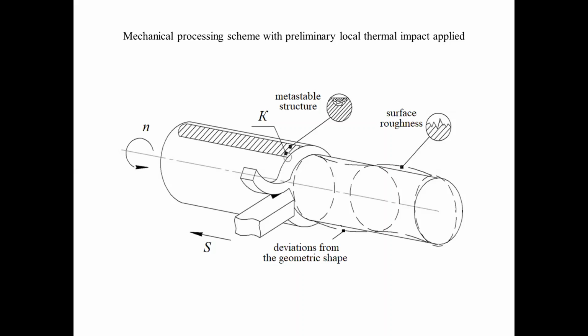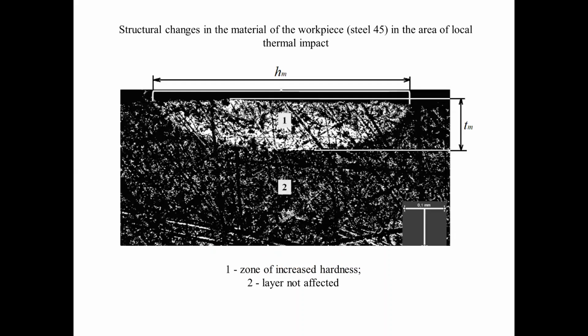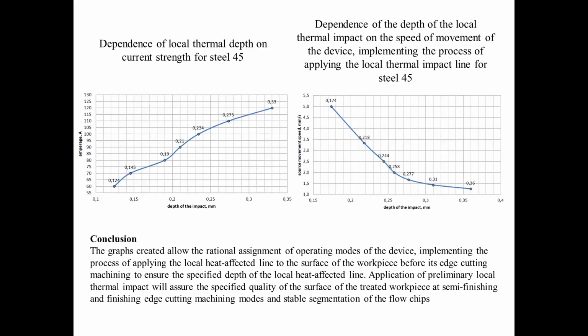The depth of the thermal impact created by the device depends on two factors: the current delivered to the contactors and the speed at which the device moves relative to the workpiece. The study, carried out when processing the Steel 45 workpiece, allowed the creation of diagrams of the dependence between the influence of current and movement speed of the device, implementing the process of applying a line of local thermal impact, on the depth of the formed zone of local impact. Here are the graphs.